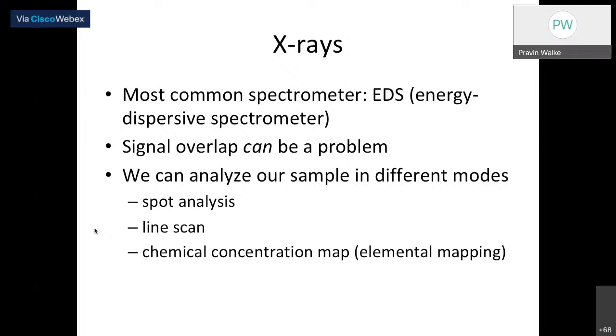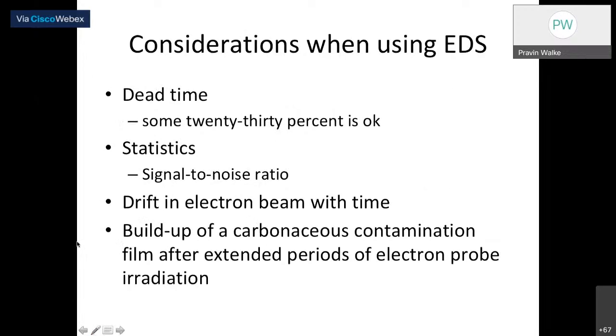So we can analyze the sample using X-ray in different modes. For example, you have the spot analysis, to see what elements are present at that particular spot, or you can have the line scan so that you can find out at which region which element is rich, or you can have the elemental mapping over the surface you have selected for imaging, as we have seen in the previous images, right?